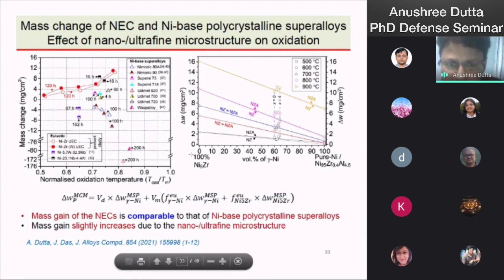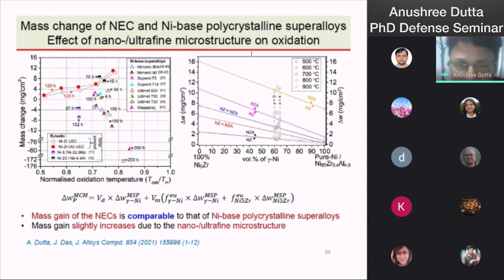And this diagram shows the contribution of the high density of the lamellar surface to the oxidation behavior. Here the individual constituent phases, Ni5Zr and gamma nickel, their oxidation mass gain is plotted here, and the mixture of the phases, similar to our nickel, zirconium, aluminum composites, lies here.